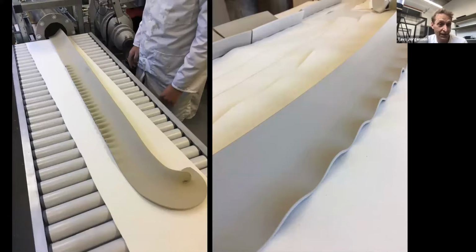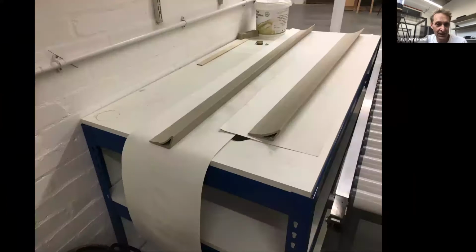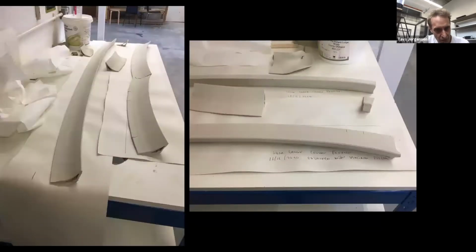But it's quite interesting from the process, coming back to some of the process aesthetics, but it's not really what we want, and you can get over it, and you can get it to flow right. And these have just been extruded with no ripples. But then when it dries, the curve comes back, because you've added more clay to one side than the other somehow, or it's more dense, and then it'll just crack and curve. So it's inherent in the extrusion.